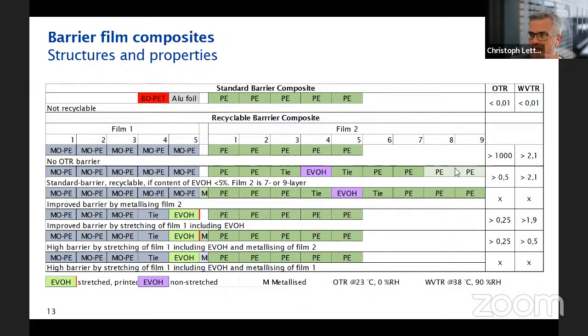So obviously, this will give an improvement. I can't comment today on how much it will improve, but it will improve. But please note, so far, no changes to the sealant film. We still go with the sealant PE film, but we did not touch it. But what we all know is that once I stretch EVOH, I will improve the barrier properties of such a film, and thus in the next solution, we do exactly that.